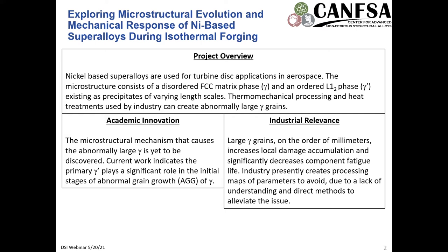And the gamma prime exists at various different length scales. We're going to call it a primary gamma prime, secondary gamma prime, and tertiary gamma prime. And those are in decreasing order of size. Primary gamma prime exists about in the microns, secondary gamma prime is about 50 nanometers, and tertiary gamma prime is about 5 to 10 nanometers in diameter.